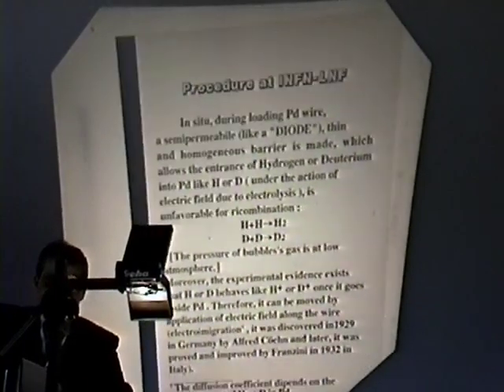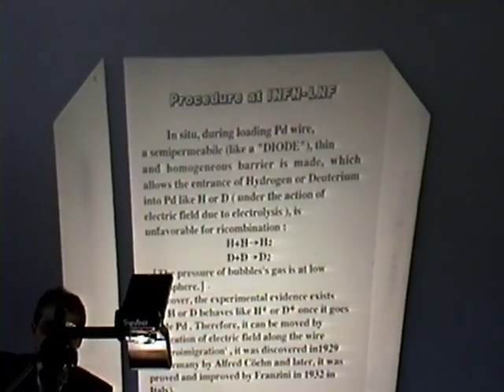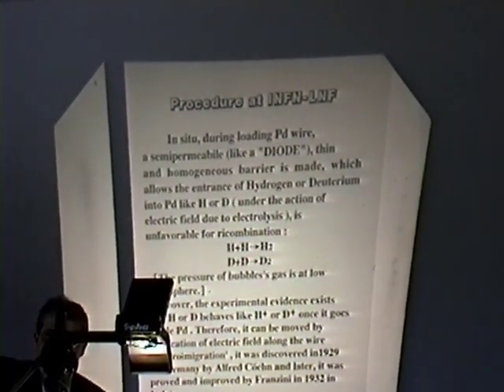The procedure is a little bit different from usual. We want to construct in situ something like a diode using a very thin amount of elements, in order to improve the loading and decrease the bubble formation, because of recombination. And when the loading is at a large enough value, we will apply some electromigration to increase the loading further, but only when the loading is large enough, not before.